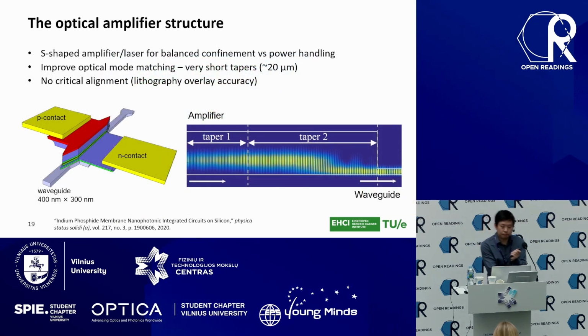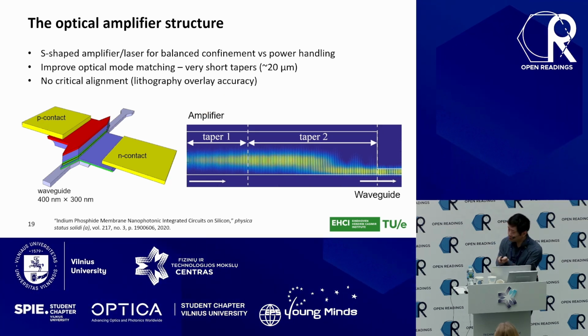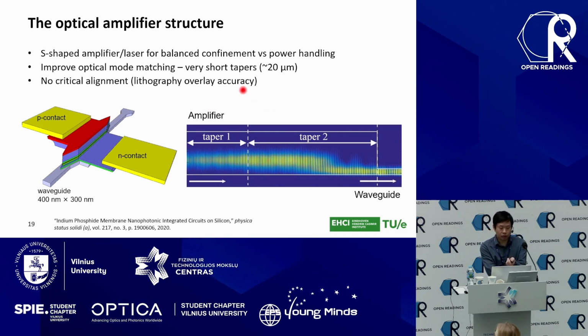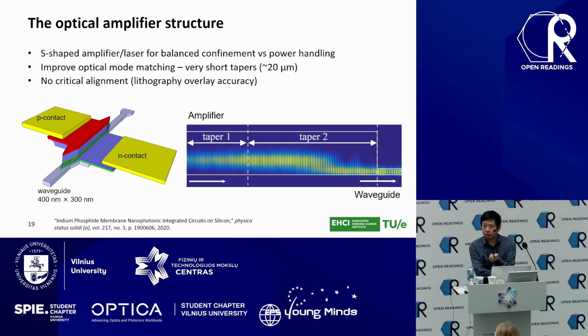First thing first, the reason we use the indium phosphide membrane structure is not only because of its high index contrast, but also because indium phosphide can give us native lasers. So we designed, on top of this membrane waveguide, a very compact laser structure. It's S-shaped, so the P and N contacts are on the two sides. And it utilizes a very short and efficient coupling to couple from the active to the passive. Because now we are not coupling between indium phosphide and silicon, we are coupling between indium phosphide and indium phosphide, the mode matching is very good.